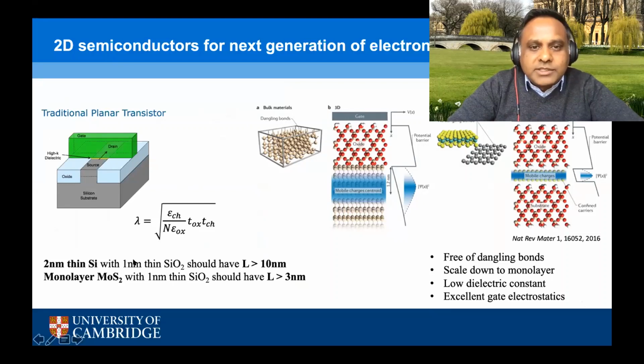One can do that with 3D semiconductors, but one runs into a problem with the introduction of dangling bonds and surface scattering states. So there's a finite limit to how much you can thin down silicon or gallium nitride or gallium arsenide. In any case, if one calculates the characteristic intrinsic channel length with the current state of the art, the scaling for bulk semiconductors is around 10 nanometers. But for naturally occurring atomically thin body semiconductors, like single layer MoS2, one can achieve, in principle, devices that are sub 10 nanometer, all the way down to around 3 nanometers.